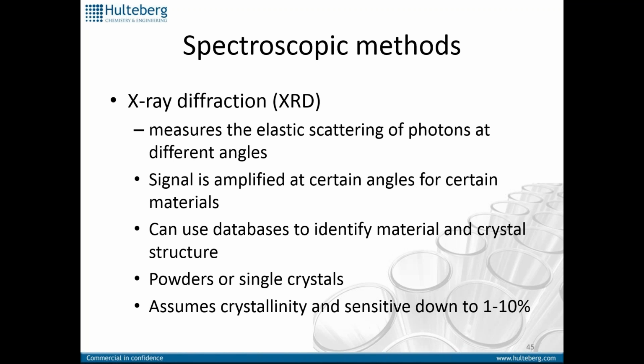Use it on powders or on single crystals, and it has to be crystalline. The drawback is that you can't see low concentrations of materials unless you spend an infinite amount of time doing the analysis. So maybe 1 to 10% is our visibility limit.